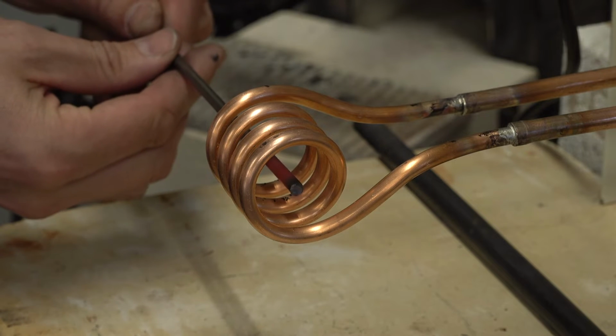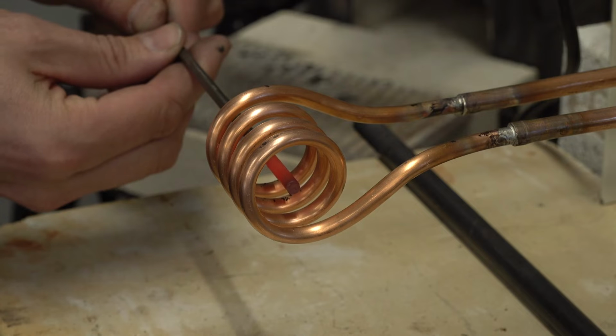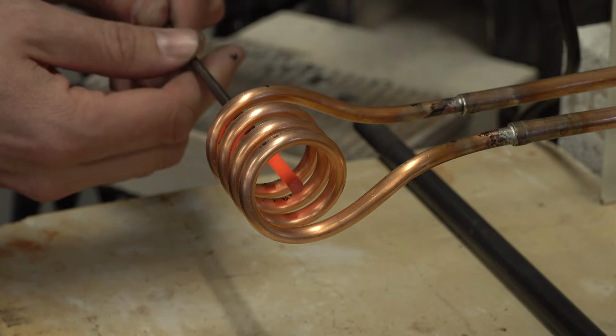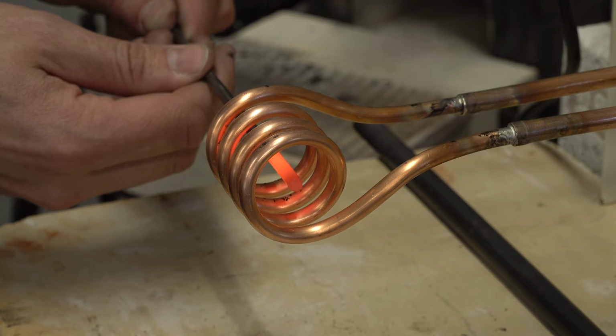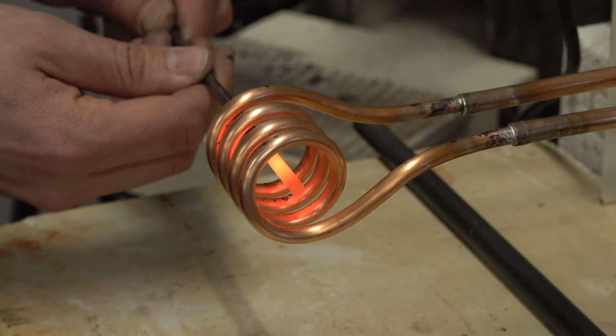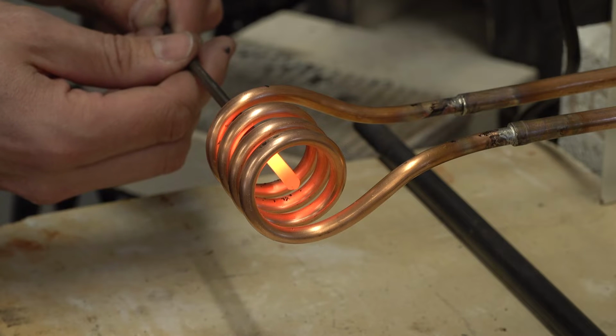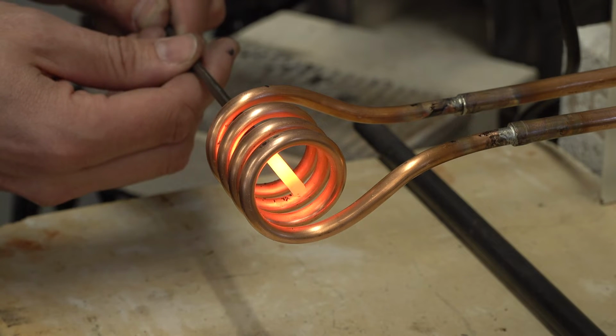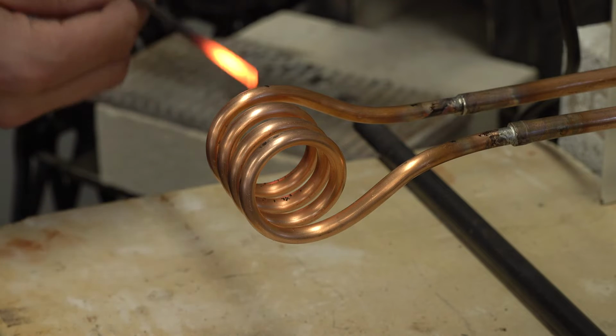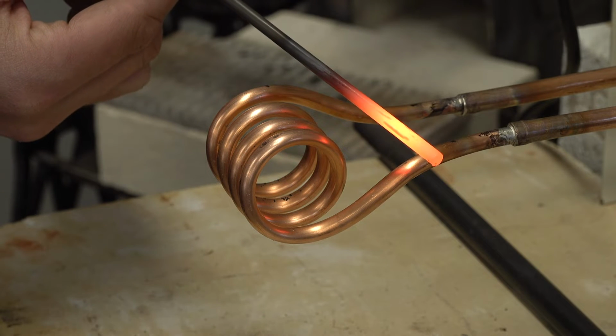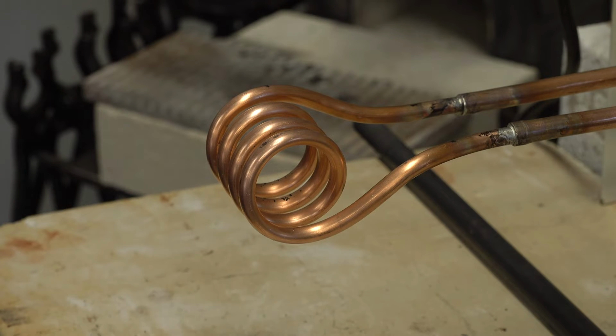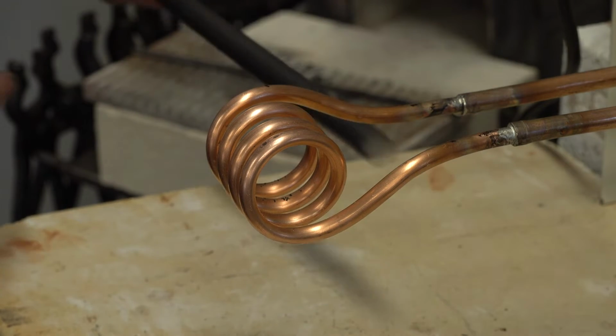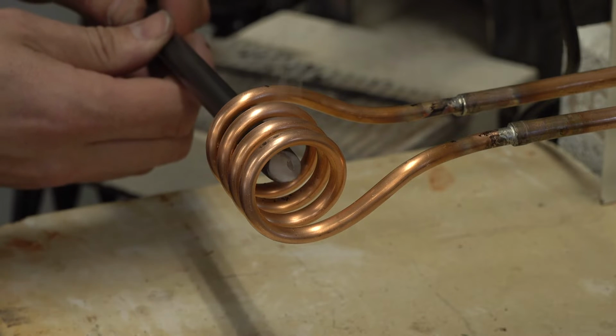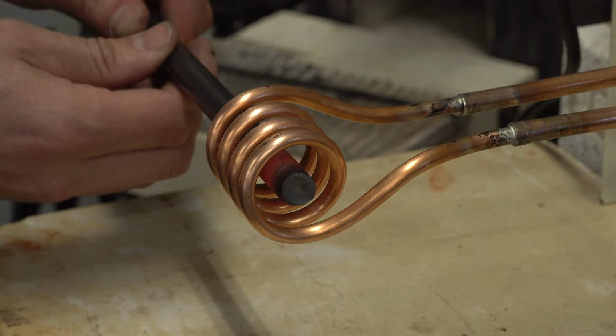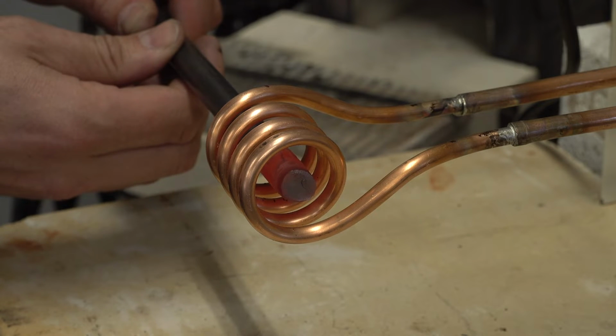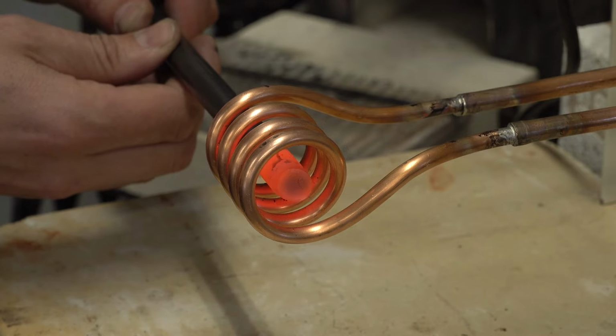Generally speaking, you want the coils to be as close to your material as possible for the most efficient heating. You'll notice here that this 1/4 inch piece of rod will only heat to orange heat, although it looks brighter on the camera, because the coil size is too big for this material. However, if I put a 1/2 inch bar in the same coil, you'll notice that it heats much more efficiently and will get up to a much brighter heat than the 1/4 inch rod can.